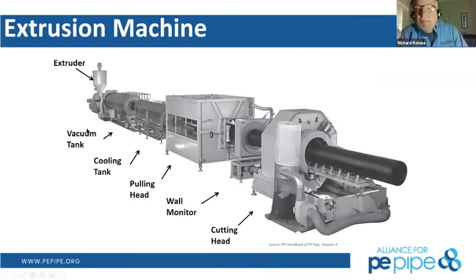This is a typical extrusion line for pipe. It's condensed a little bit, but way at the far end back there, although it's not a great descriptor, because a lot of people don't like showing these pictures of how they produce pipe, since it's kind of their secrets of production. Anyways, it melts the product and mixes the carbon black into the natural resin. We extrude it into a round profile, and then we have to vacuum and cool at the same time to obtain the sizes that we want.